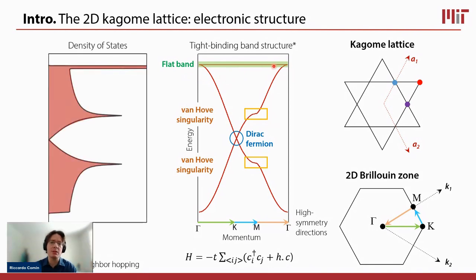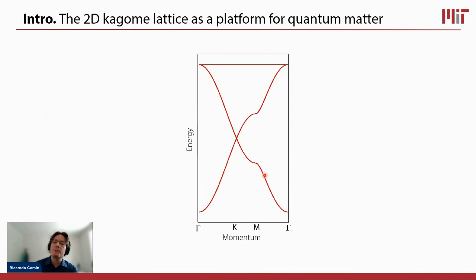And so if we look at the density of states, so if we count how many electrons exist as a function of energy in this band structure, we see that at the Dirac point, where we have the Dirac fermions, the density of states is vanishing. So there's essentially a vanishing number of electrons here. At the flat band, the number of electrons is diverging because all of the electrons have exactly the same energy. So we have like a delta function of energy in the density of states. And then at the Van Hove singularity, we have a divergent density of states because of the dispersion becoming locally flat.